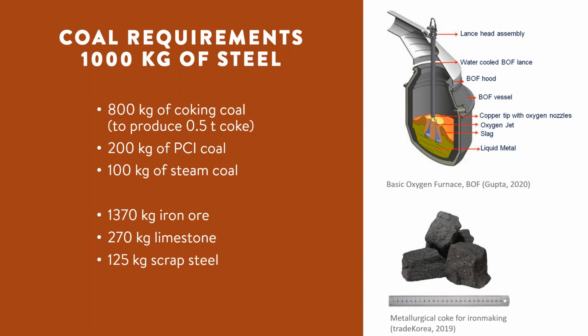Like the blast furnace process, the interactions between the oxygen, the carbon, the ore, and the additives and other compounds is a very complex process. There's a whole series of chemical equations involved in that, but I won't have time to cover that here. But overall, by this stage, the integrated steel mill has probably consumed about 800 kilograms of coking coal, up to 200 kilograms of PCI coal, maybe 100 kilograms of steam coal to produce a single ton of steel, as well as all the other raw materials that you can see here.